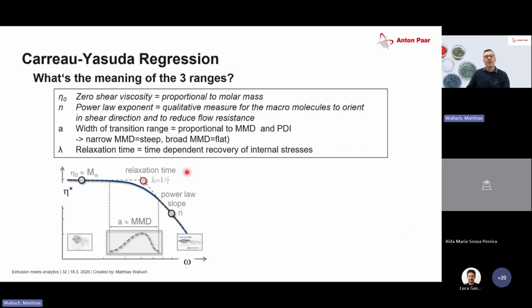Now, what can we do with the data that we just measured? Carreau-Yasuda is one of the regression models, and we can use this to get information about the shear viscosity, which correlates to molecular weight, which we already saw in the shear tests. We get information about the slope here, which is correlated to the flow behavior of the material, and we get this a value, which is correlated to the distribution of the mass, which I already showed you as well. And we get this nice crossover point here, which is lambda, the relaxation time.